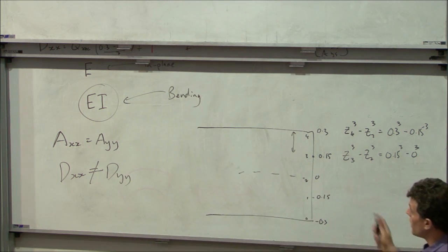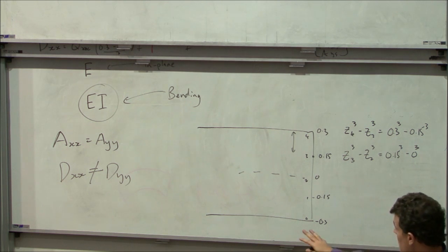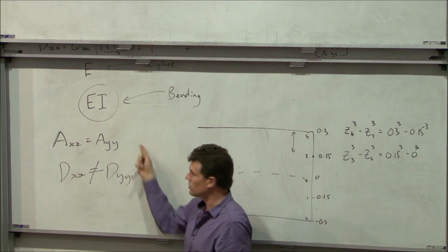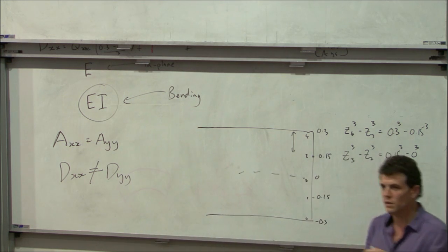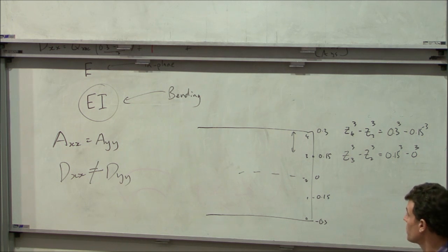So I'd ask you to go and have a go at that calculation yourself. But the effect that this has is that, because these two things are decoupled, we can make laminates that have very different in-plane behavior than they do bending behavior.